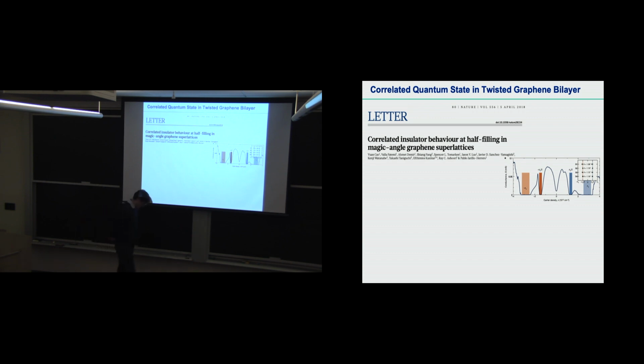What the Pablo's group actually showed, out of a few years of work, is that things can be different, especially when you stack graphene together such that these Moiré patterns can engineer graphene band structures. In particular, you can engineer band structures such that you create a very, very narrow band. And of course, this narrow band, at the middle of it, promotes a large density of states, which can actually create some correlation effects.